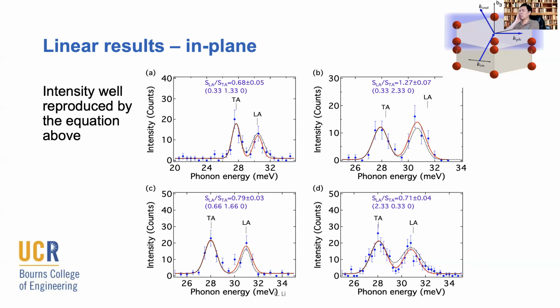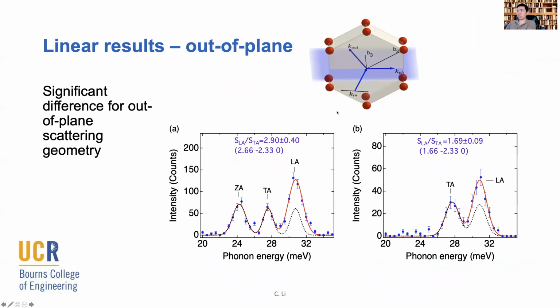Then we spent more time thinking, and what we realized is that all those phonon modes actually have a circular motion in plane. So that might not couple with the neutron very well. So what we wanted to do was flip the crystal and do a scattering that is not in the basal plane. That's what we did next. And it turned out we see something that is completely different.